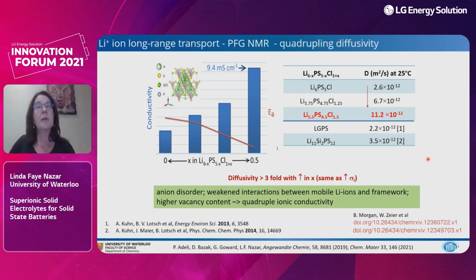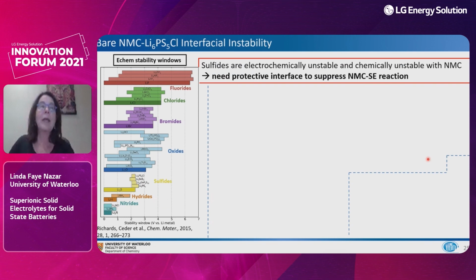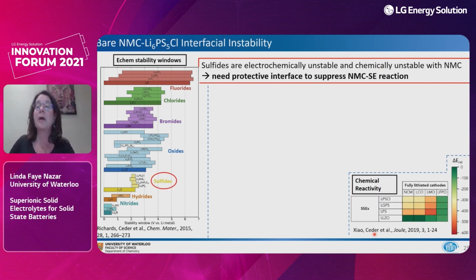And so that then led us to think about halides more and more. For some of you perhaps it's well known that a lot of sulfides do not have great interfacial stability with promising cathode materials such as the NMC class. And that is because they're electrochemically unstable and chemically unstable with NMC. This is shown by a nice paper by Gerbrand Ceder's group, where they look at the chemical reactivity of these materials with a variety of different cathodes, lithium cobalt oxide, lithium iron phosphate, etc. The electrochemical stability is also shown by calculations, and you can see that it's limited to about 2.5, 2.7 volts.